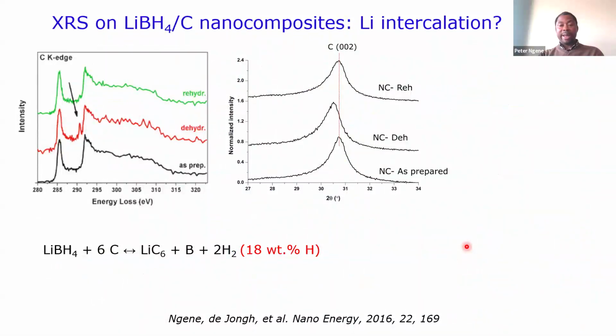But then I came back to the XRD. Of course, you cannot see the active material, which is lithium borohydride, but actually the carbon, because it's graphite carbon, it has some peak around 30 degrees 2 theta. And then we look at this again to really figure out what is going on here, because we do see that something is changing with the carbon. If you look at the as-prepared sample, and then this is the nanocomposite after dehydrogenation, we remove the hydrogen, you see this peak has shifted towards lower 2 theta degree. And when we do rehydrogenation, we do see that it shifted back.